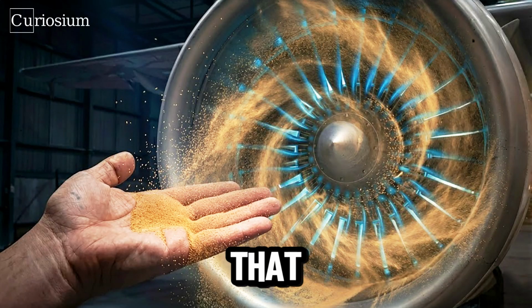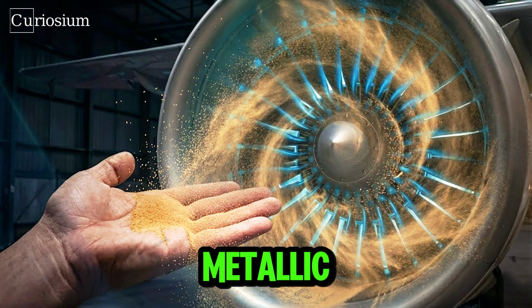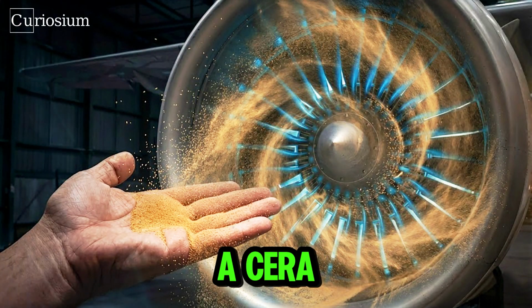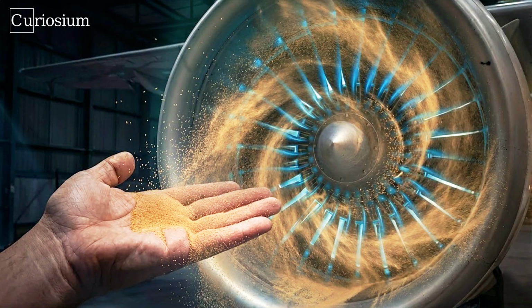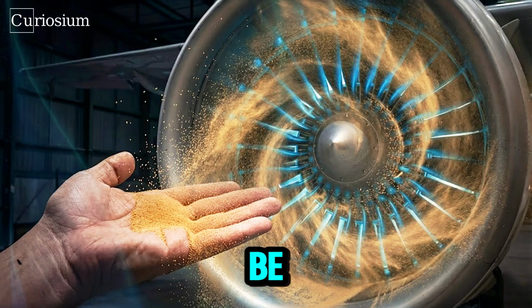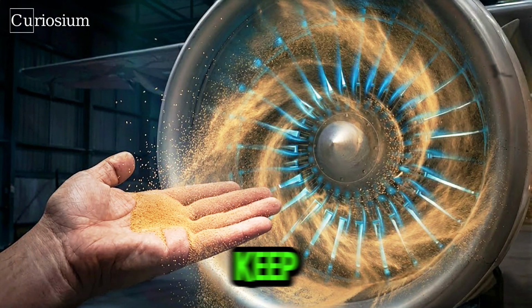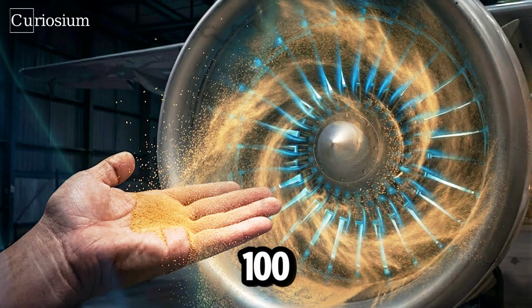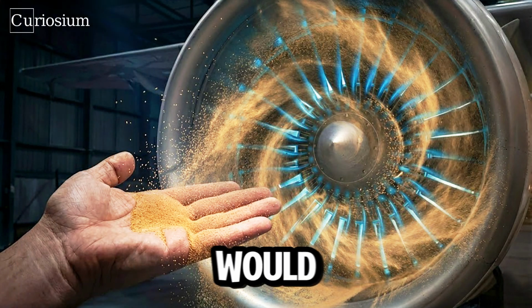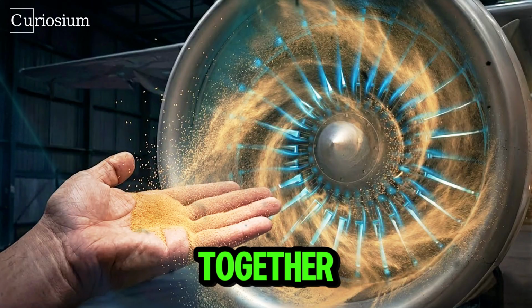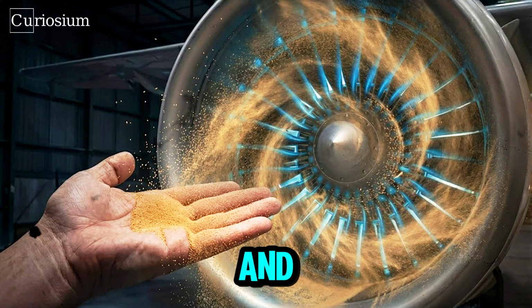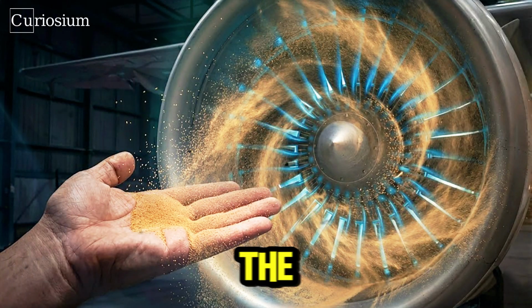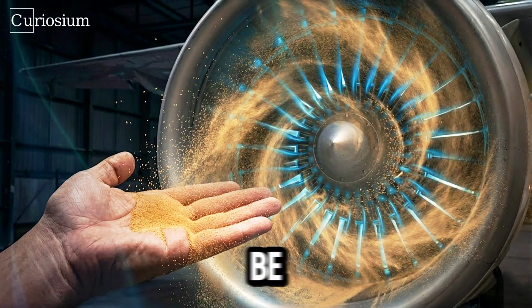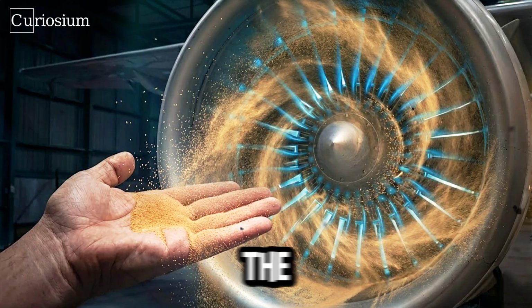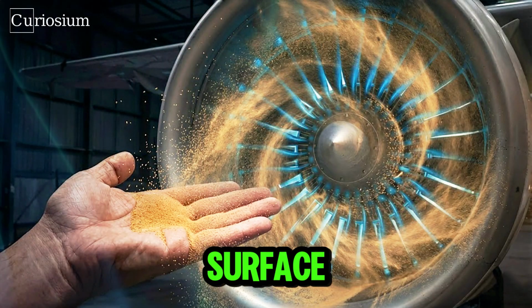On top of that, the blade is coated with a thin metallic bond coat and then a ceramic thermal barrier coating. Even though this ceramic layer can be thinner than a millimeter, it can keep the underlying metal more than 100 degrees cooler than it would otherwise be. Together, the internal cooling and external coating allow the gas flowing past the blade to be significantly hotter than the effective temperature at the metal surface.